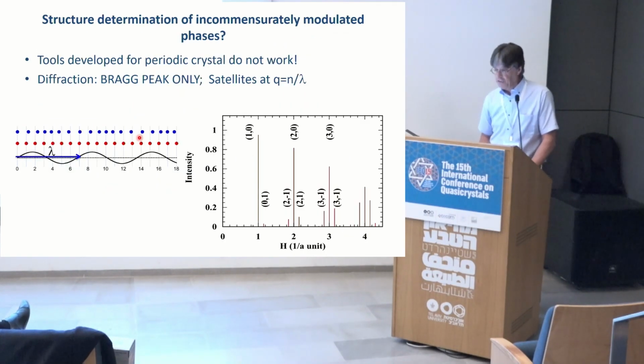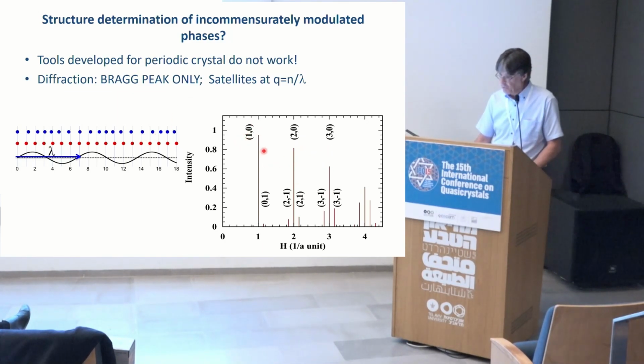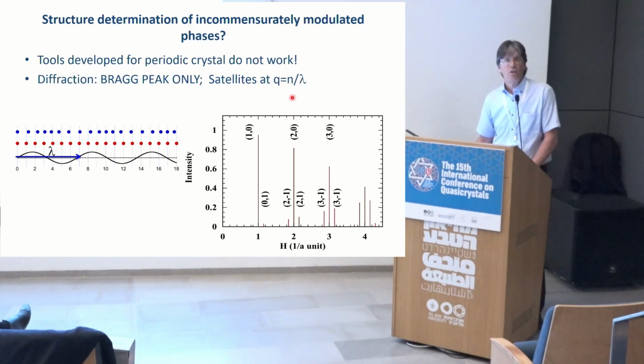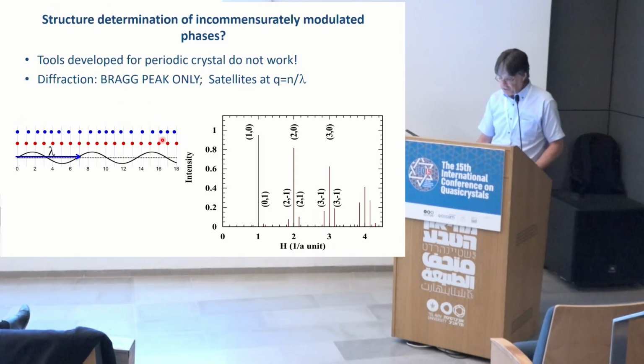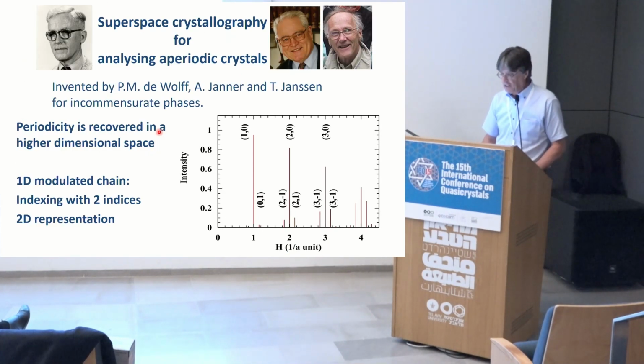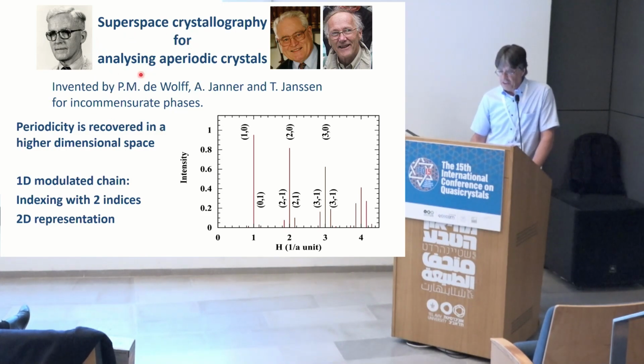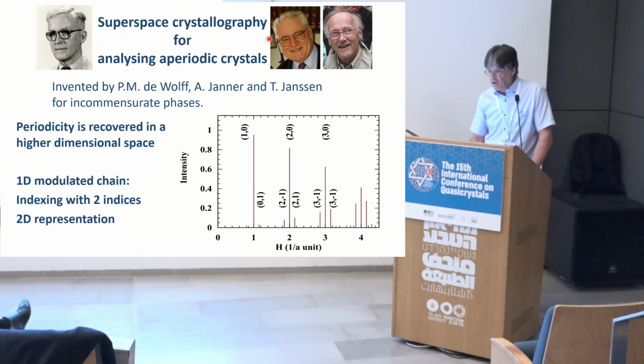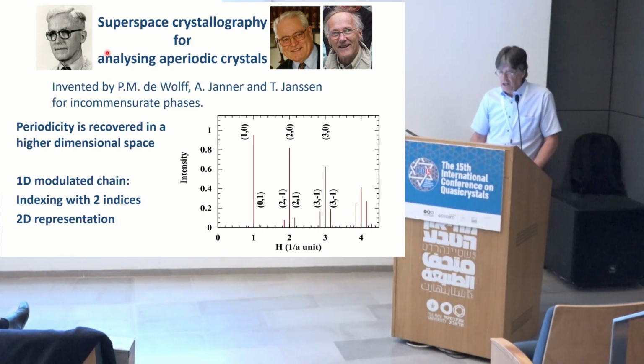And if we look at the diffraction pattern of this non-periodic structure, you have bright peaks here. These are actually a trace of this underlying periodicity. And we have so-called satellites here, here, and here, whose distance from the main bright peak is 1 over lambda, lambda being the wavelength of this modulation. Of course, here it's a perturbation, but nevertheless, it was derived in the 80s by Pim de Wolff, Aloysio Janner, and Ted Janssen, a method to analyze the structure of this non-periodic yet ordered structure.